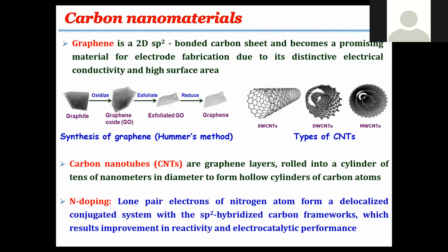So generally, the electrocatalytic activity and the electronic properties of the carbon material can be improved by the doping of heteroatom elements, especially nitrogen doping. The lone pair of electrons of nitrogen atom form a delocalized conjugated system with a sp2 hybridized carbon framework, which results in improvement in the reactivity and electrocatalytic performance.